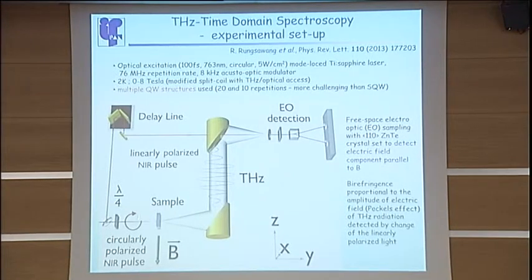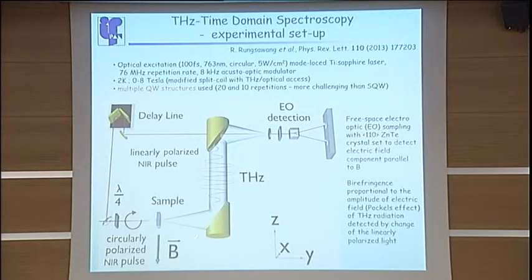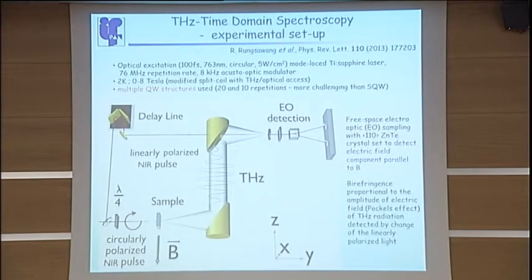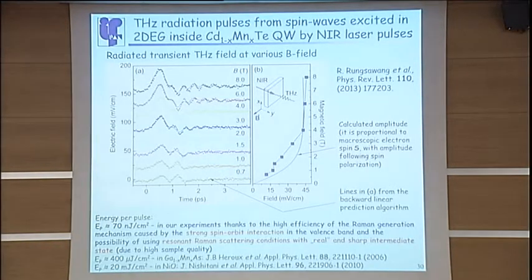They excited the sample with circular polarized light, collected the radiation by two parabolic mirrors, and detected the transient by free space electro-optic sampling, which was set in such a way as to detect the electrical field which is parallel to the magnetic field. And here is the result.